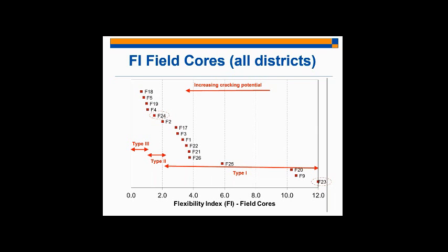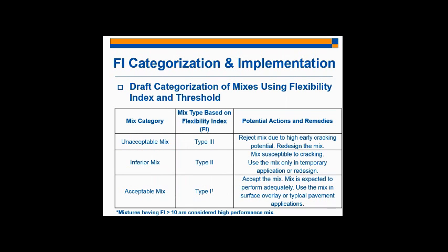And so I mentioned the three categories. So you have type 1, type 2, and type 3. So essentially what would happen is if your mixture falls in the type 3 region, which is all the way to the left of the flexibility index spectrum, then you would reject the mixture due to high early cracking potential, and you would redesign. You would make modifications to the mixture and then rerun the test, and see if this mixture still falls in the type 3 region.